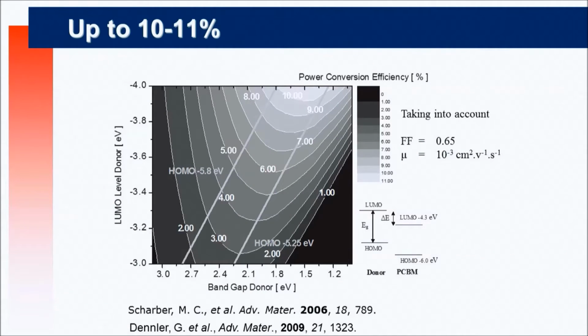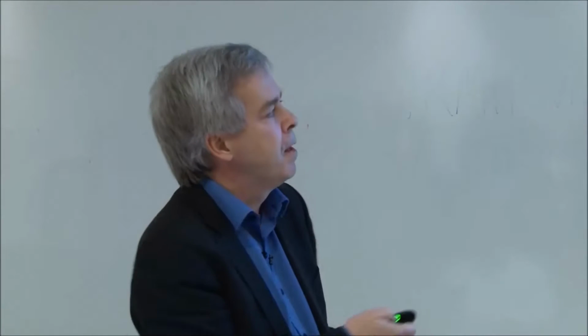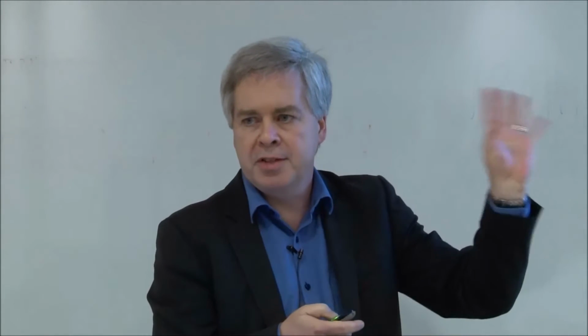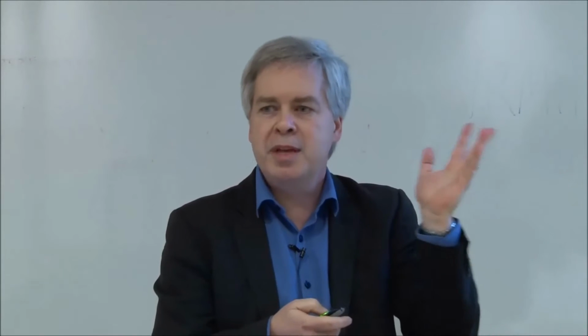Physicists from Konarka at that time made theoretical calculations, and I don't want to go into the details here. This is the fill factor. Let's say the efficiency of the overall solar cell somehow. But the point here is very important: mobility in those glassy, not so crystalline materials is about 10 minus 3. With amorphous silicon, it's about 1. Crystalline silicon is about 100, 1000. Here it's about 10 minus 3, 10 minus 2. When we get 1, we're very, very lucky. Fullerene is about 10 minus 3. So the limitation here is really the mobility of the charge carriers.